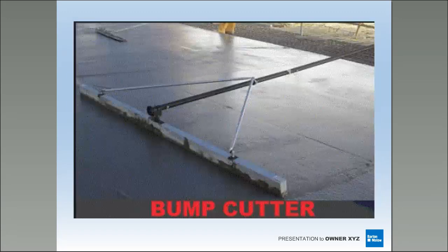Now, the one I will caution you on is the bump cutter, all right? The only time I will ever use a bump cutter is when super flat is more advantageous than the polish. If I have to hit a very high FFFL number, there will be a bump cutter. If I have a polished floor with that very high FFFL number, we will have a discussion about maybe having some, I like to call them bald spots, stone spots, because this bump cutter is going to cut and move that cream, and I'm going to wield it any way I can to get the flattest floor I can. It's not going to help the polisher because I'm displacing that cream and making it uneven to get my flat surface. So this is a very important discussion with the owner on what's more important, the look of the polish or the flatness of the floor.